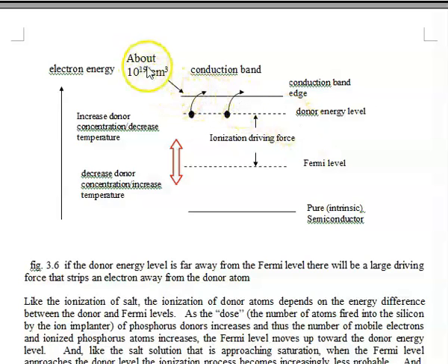I should just mention here, I put this on the diagram: the amount of salt which would define a saturated salt solution has an analog in the silicon world of the amount of electrons which the conduction band is able to support without revolting, and that's about 10 to the 19th electrons per cubic centimeter. And that indeed will give an extremely small resistance.